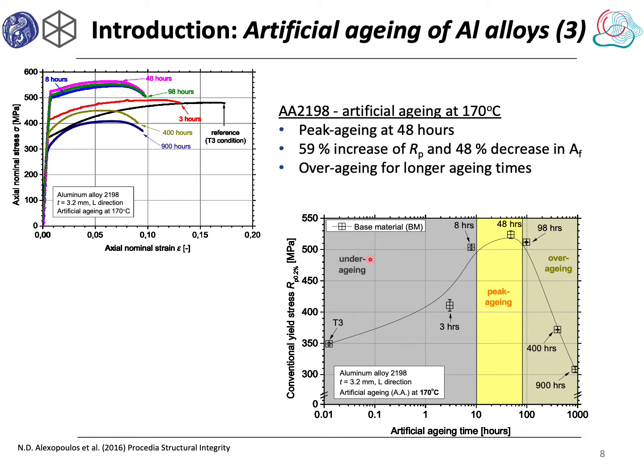A plateau in the yield stress was noticed from 8 hours up to 48 hours aging time, which is characteristic for the peak aging condition. Finally, by further increasing the artificial aging time to 98 hours, there is an essential decrease in the yield stress due to the coarsening of the precipitates, so this heat treatment condition is considered to belong to the over-aged region.